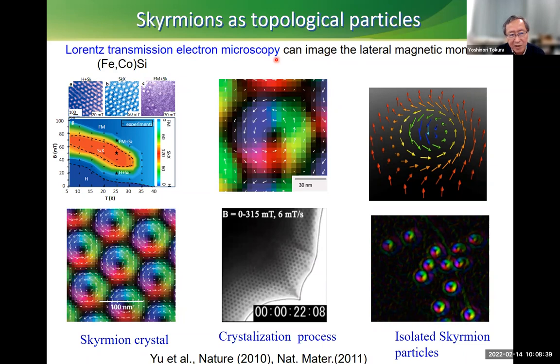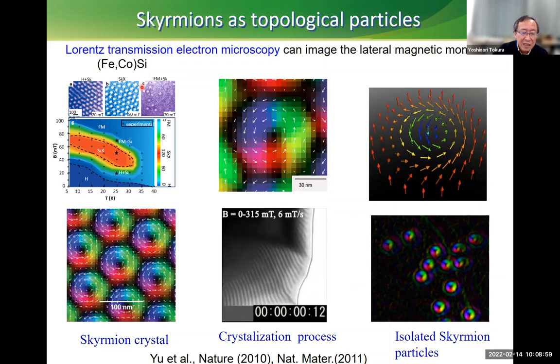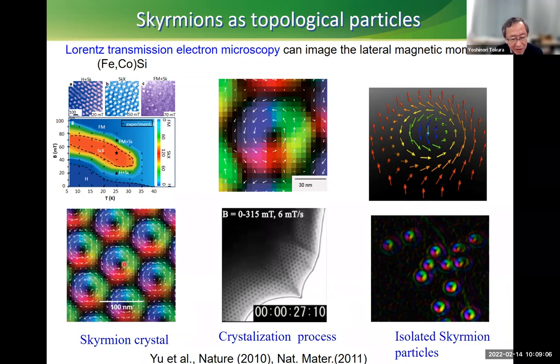I skipped the detail of the methodology of the transmission Lorentz TEM, but it can define the two-dimensional direction of the moment. And this is a picture for the case of iron cobalt silicide, just like manganese silicide or iron germanide. It's almost the same structure. And you can see that this is the actual analyzed data of the Lorentz TEM. And you see the very nice crystal structure of this spin vortex.